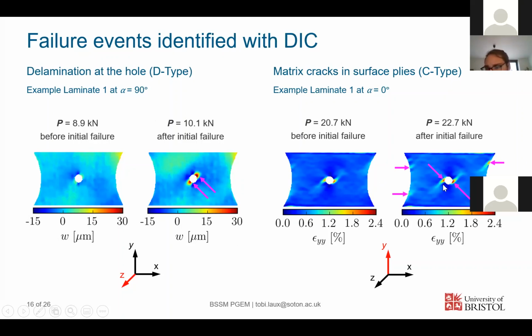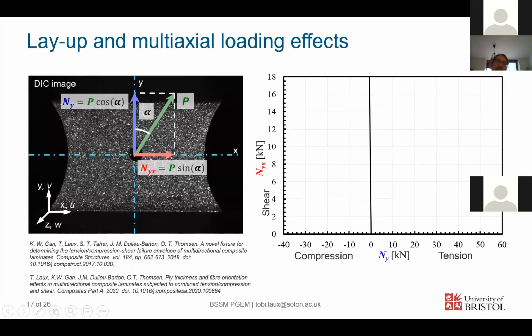And that's something you typically would see in strain fields. Here the vertical strain by these strain concentrations. So now back to the failure envelope. So I show you now the thick ply laminates to start. And now, of course, the question is, how does the layup 2 compare? And so the layup 2 actually is a lot stronger here.